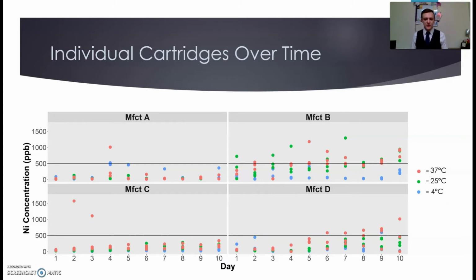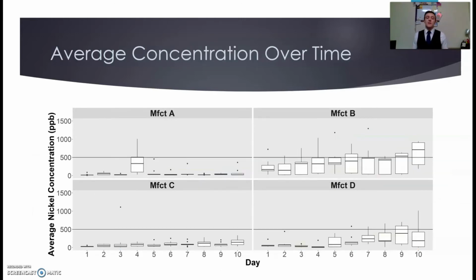However, what this plot really starts to illustrate is the tremendous amount of variation within individual days. We actually experienced a tremendous amount of variation within triplicate cartridges themselves, cartridges that were sampled on the exact same day and subject to the exact same conditions. In fact, the average relative standard deviation among these cartridges was over 50%, a variation that can really be illustrated in this plot, in which the same data is expressed as box plots.